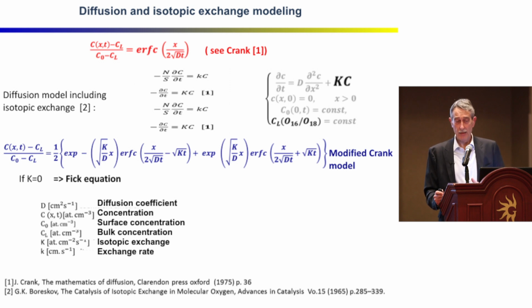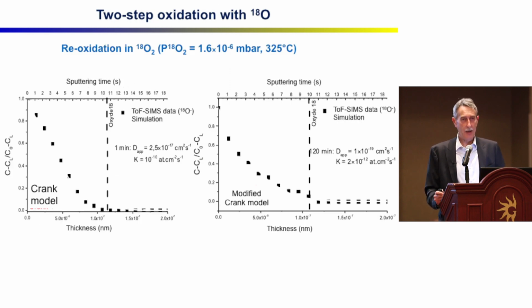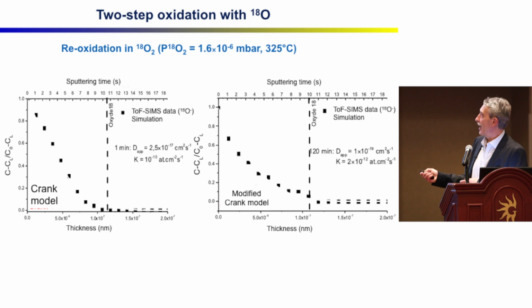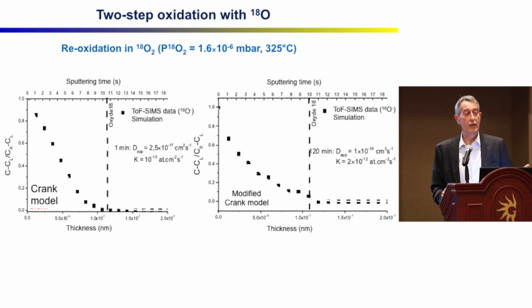And then we can fit the ToF-SIMS profile. These are portions of the profiles I've shown before that were renormalized. The black dots are the experimental data from the time of flight SIMS, and the red curve is the fit using the equation I've shown before. So from that, we can not only find out what is the species that is diffusing in the oxide, but we can calculate the diffusion coefficient. And it's very interesting because not only do we need this number to predict the evolution of the oxide in a nuclear power plant, but we need to know whether this number will vary with time or not.